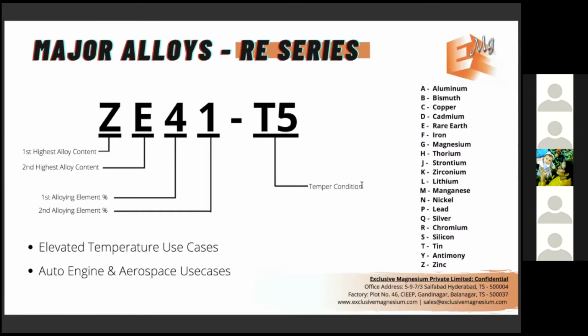The third major series used in magnesium globally is the ZE series, which is the rare earth series. ZE is zinc, and E stands for rare earth. The reason this alloy is majorly used is because other magnesium alloys have lower creep resistance, right? At elevated temperature, they're not great materials to be used for engine use cases and things like that. So there are a bunch of rare earth alloys now, which are used specifically for auto engines and aerospace use cases, which would be subjected to elevated temperature and need to maintain a certain amount of strength even at that elevated temperature. Anywhere between 200 and 350 degrees, you would get great strength from these alloys.